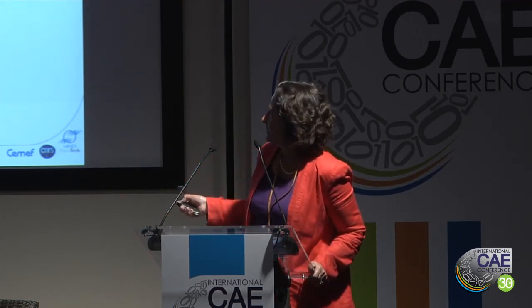So, the microstructure. It's very important to be able to simulate the microstructure evolution during forming, but also during heat treatment, because sometimes there are different and strange things appearing, and the industrial people, especially people working in aeronautics with superalloys, are very interested to understand what is the origin of this strange growth of grain and why in some parts there is a very large grain and other parts very small grain. And the question is, is it important to have a small grain, or is it not very important to keep this very large grain?